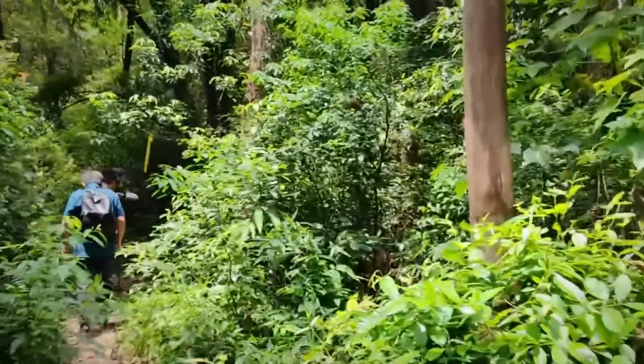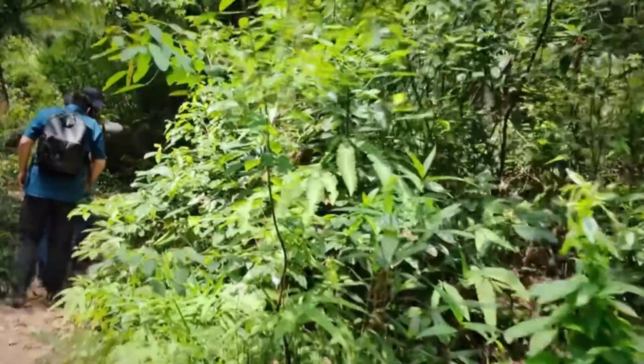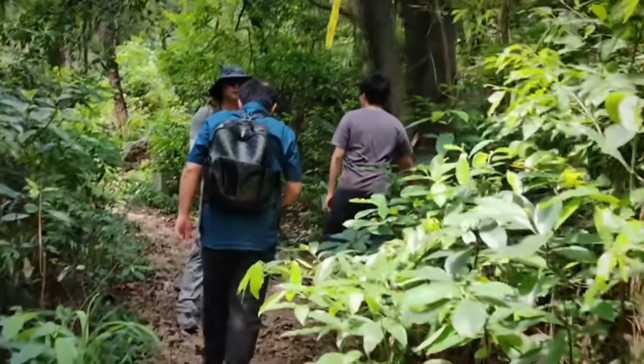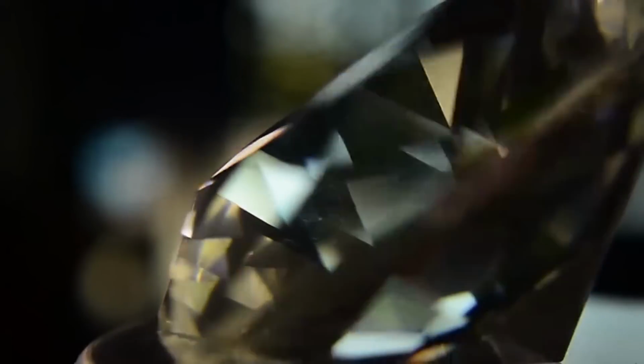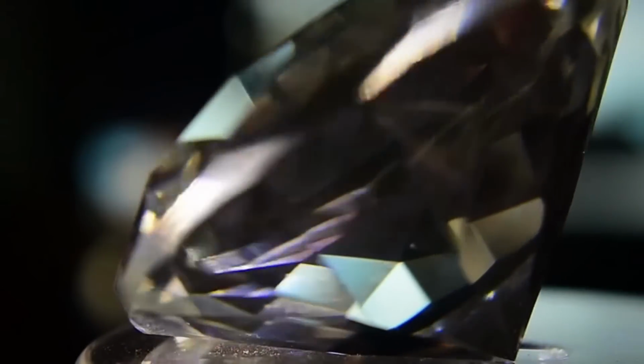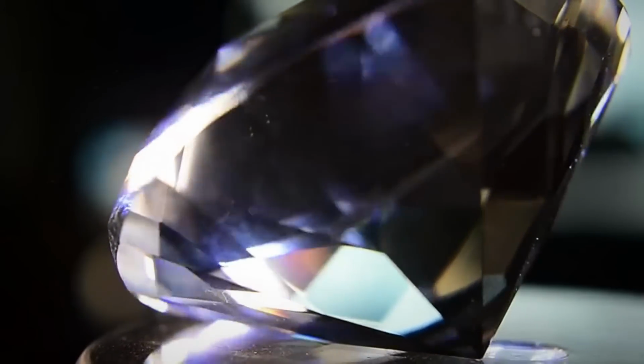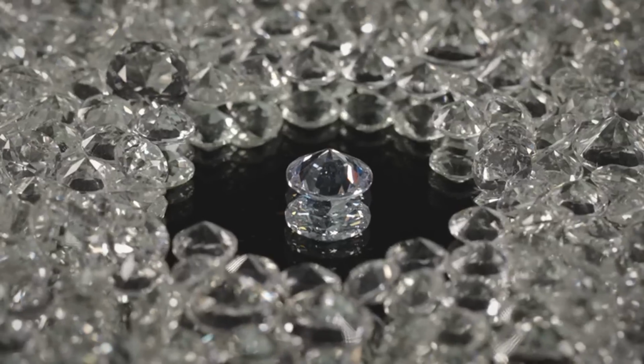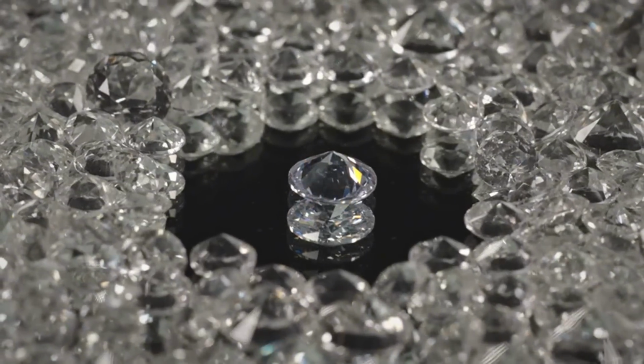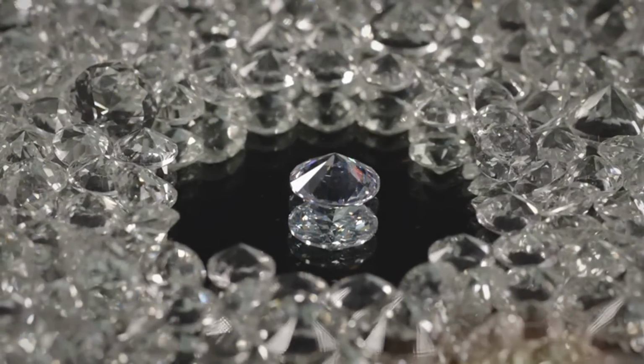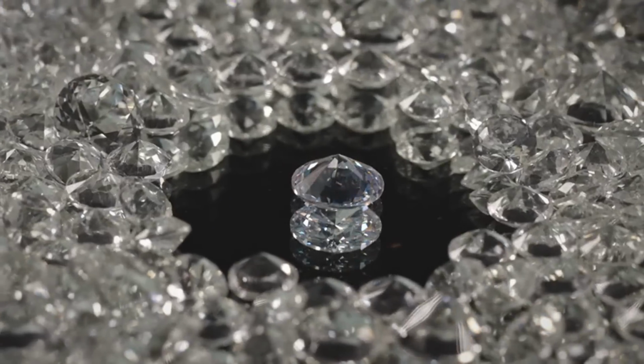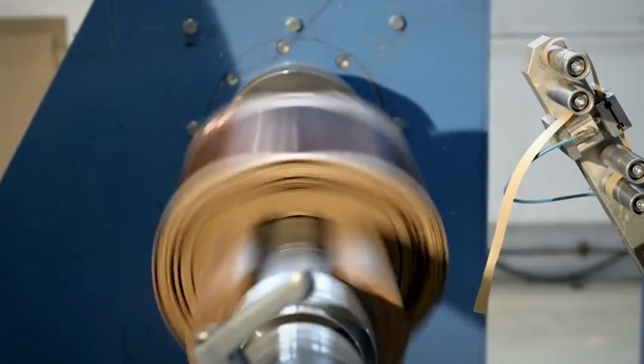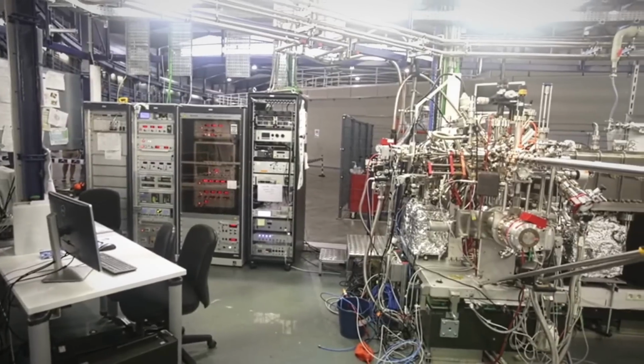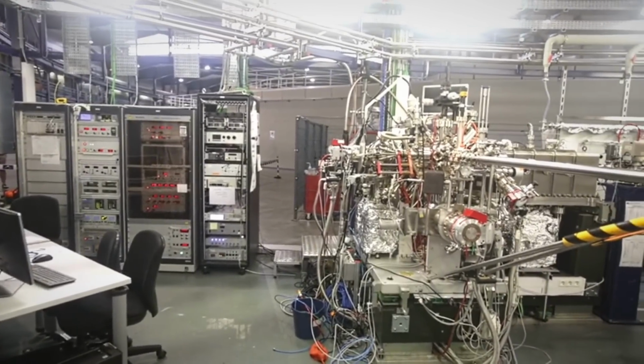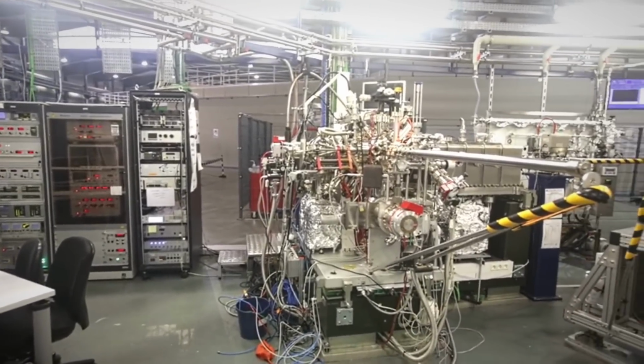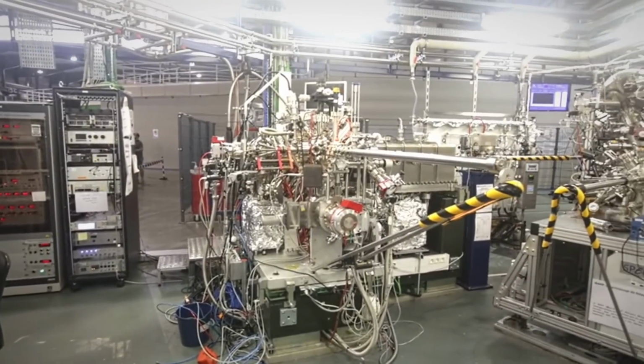But a sharp-eyed appraiser flagged one critical inconsistency: fluorescence under short-wave UV. It was too stable, too uniform, across the entire surface. Natural diamonds rarely glow in perfectly symmetrical saturation under both UV regimes. This was the first red flag. Upon further inspection, the exposed diamond displayed facet doubling under a high-magnification gem scope, a subtle optical distortion indicative of double refraction, not found in diamond.